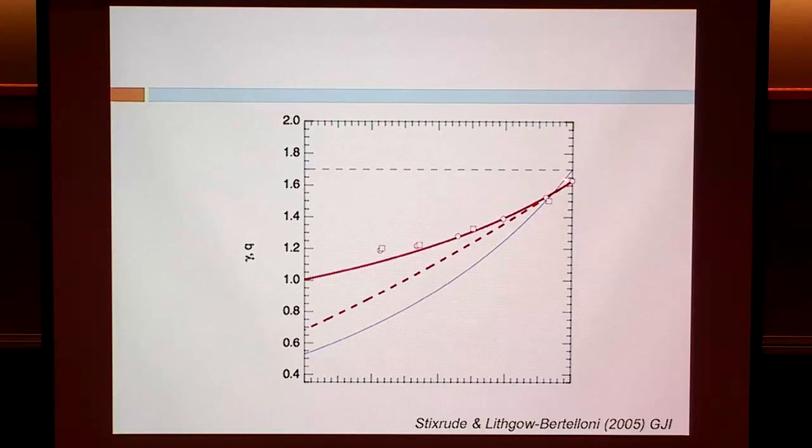Instead, we have a different theory for how Grüneisen parameter depends on compression. All we do is we expand. We use the Taylor series expansion again. We expand the characteristic vibrational frequency as a Taylor series in the Eulerian finite strain. And with that, we get this curve for the Grüneisen parameter and this curve for Q. So Q is actually decreasing on compression.